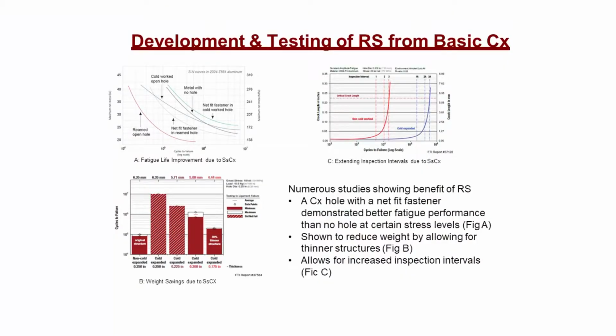Here's where it really starts to play into crack propagation for our structures, is in the time it takes for a crack to go from visible to critical. So if you look at these curves, here is a hole that is not treated, and here is one that is treated. So the crack growth, once it hits critical length, is about the same. So that vertical climb is the same. But what's telling here is the change on the x-axis. You get a much greater length of time before that crack starts to grow between initiation and critical length. So that's where you get that real improvement.